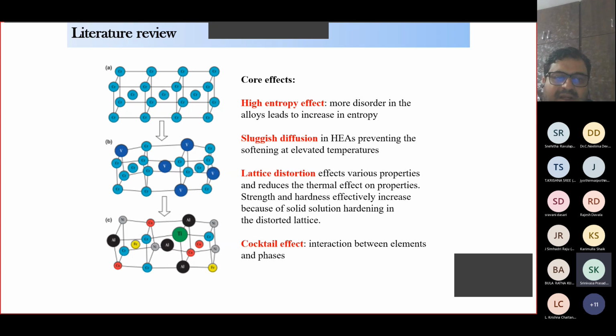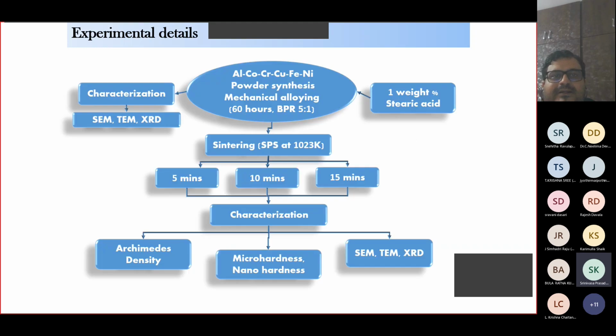But later on, when these were proposed way back in 2008 or so, now it's 14 years later, in 2022, most of these things are not really possible. For example, sluggish diffusion. When you expect that diffusion is slow here, diffusion of what? For example, there is no solute, there is no solvent here. Everything is in the same proportion. You never know what is diffusing and how it is diffusing. As a result, diffusion is not really slow when it was actually measured. High entropy effect is there, and lattice distortion is also affecting the properties. Cocktail effect is something again that has to be seen experimentally.